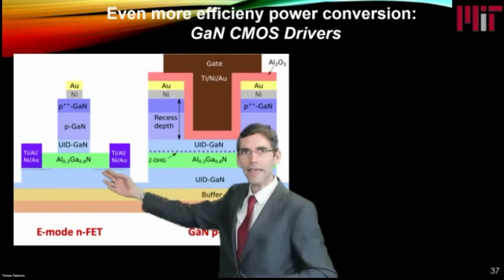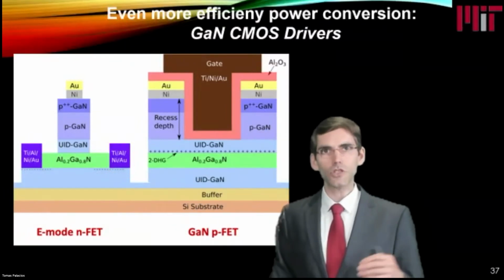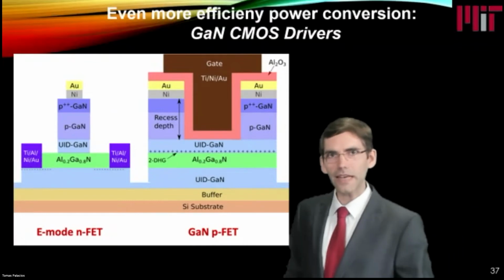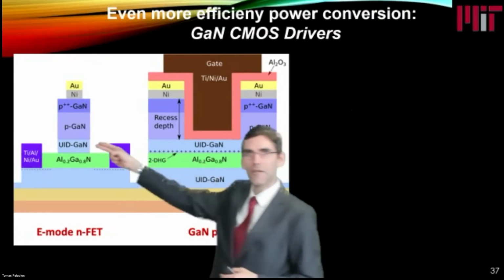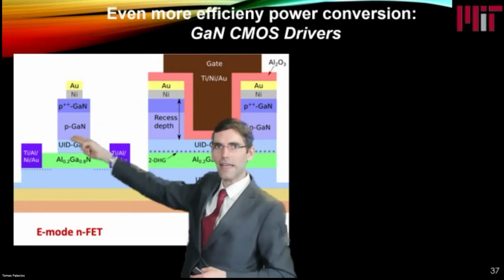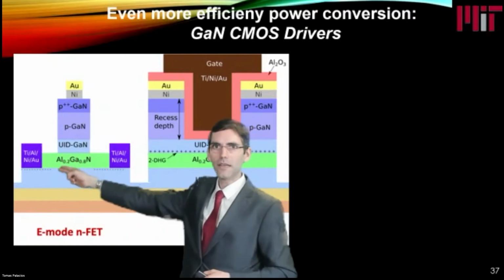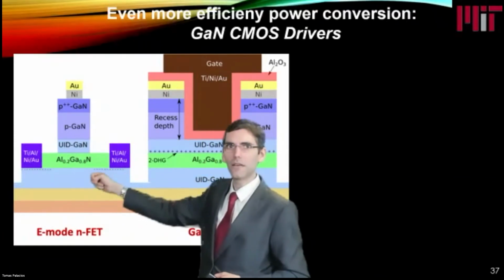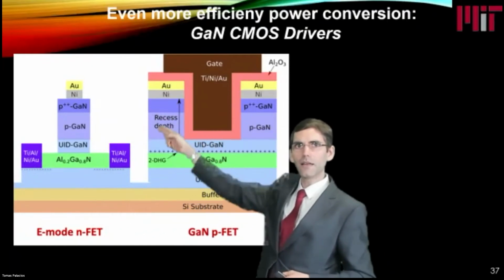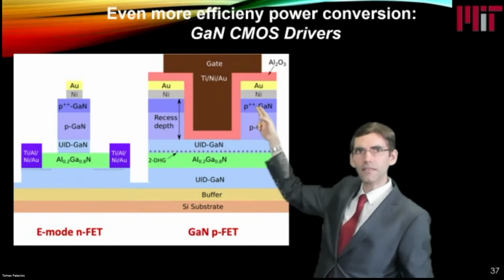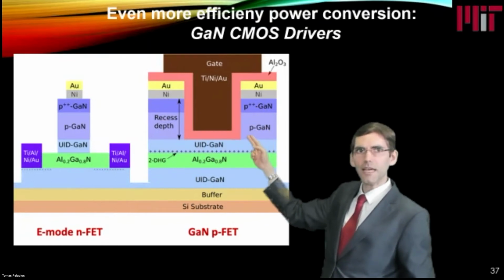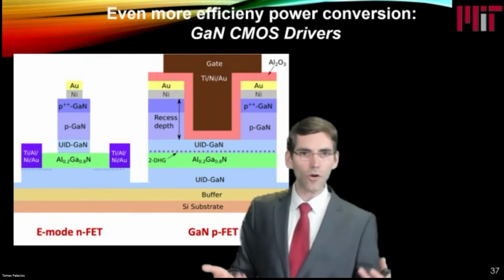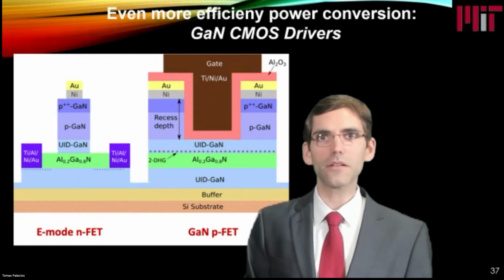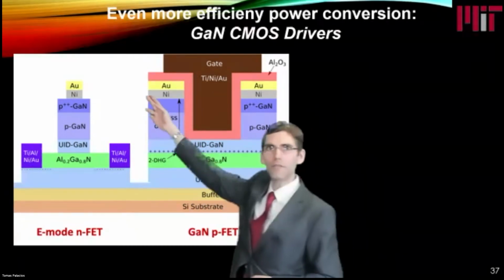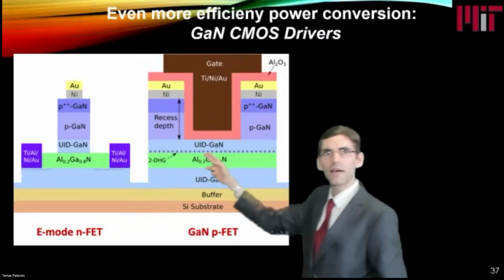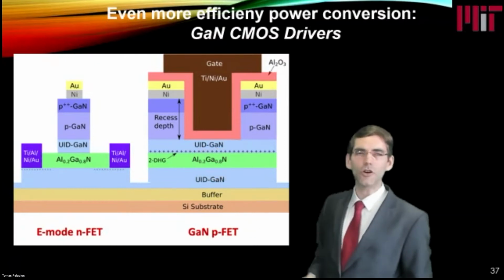But then, next to it, we fabricated a p-type channel gallium nitride transistor. And for that, we took advantage of the fact that the p-type gate stack in the enhancement mode device is actually depleting the two-dimensional electron gas. So what we did was to keep that in the access regions of our p-type device and use the p-type doping to induce the holes that we needed in our p-type channel transistor. And then we have the source, the drain, and the gate through this UID and intrinsically doped gallium nitride.